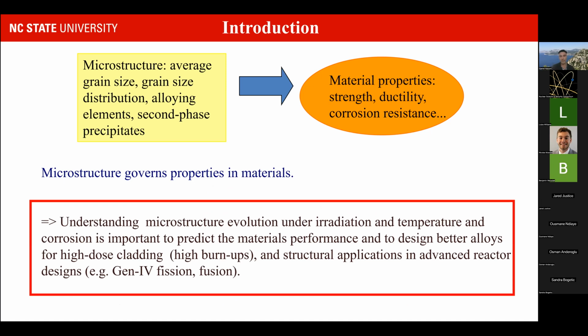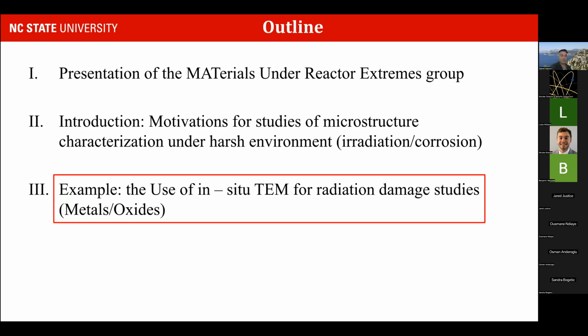So understanding how the microstructure evolution happens under irradiation, temperature, and/or corrosion is extremely important to predict the material's performance and to design better materials, whether it's for Gen 4 reactors or for any kind of extreme environment. So for that matter, I'm going to now go over the specific technique that allows us to study microstructure evolution under irradiation, and that's through the use of ion irradiation coupled with transmission electron microscopy.